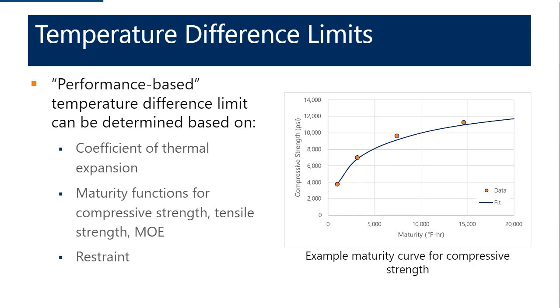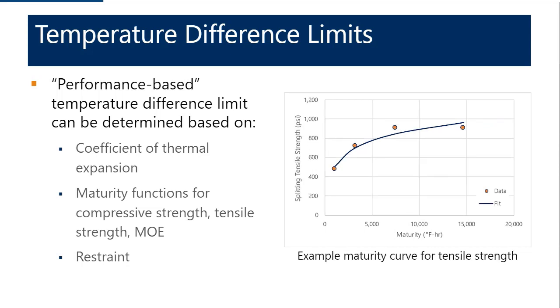This is commonly used even in pavements and bridge decks and other applications to estimate the in-place strength of concrete based on its temperature, without actually having to measure the compressive strength of cylinders or cores. A similar relationship can be developed for tensile strength, modulus of elasticity, and so on. And using these relationships, combined with the coefficient of thermal expansion and the restraint that's present within a particular element, you can use that to determine the risk of thermal cracking in a placement and then the allowable temperature difference so that that risk is minimized.